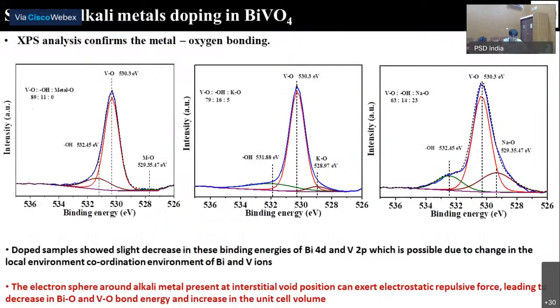Then further XPS data we have used to analyze it. In this, the binding energy for the bismuth and vanadium is decreasing. That again shows that when our dopants are going to the interstitial positions, they are exerting some electrostatic repulsive forces. Due to that, our bismuth oxygen bond and vanadium oxygen bond energy is changing, and because of that, the bond length might be increasing. That's the reason for the increase in the unit cell volume. And further, with this oxygen XPS peak, you can see the maximum interaction in the case of sodium. So sodium has the most effect in the crystal lattice.